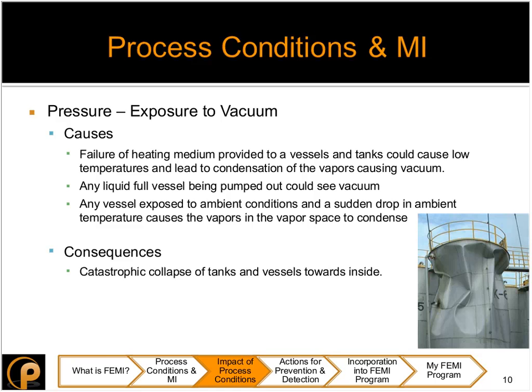Another scenario that we see for vacuum failure is any vessel that is exposed to ambient conditions where there is a sudden drop in the ambient temperature, which causes the vapors in the vapor space of the tank to condense. What happens is a catastrophic collapse of the tank towards the inside. And the image is actually a pretty good example of where the tank did not have adequate vacuum protection and a pump out scenario was happening at this tank.